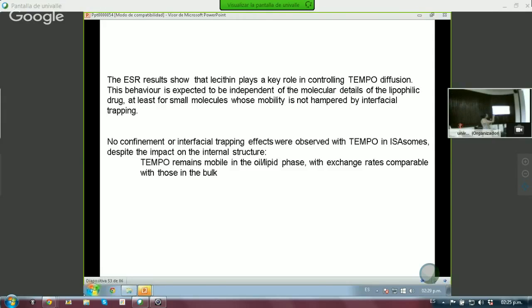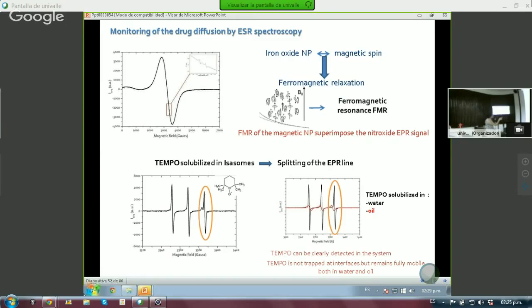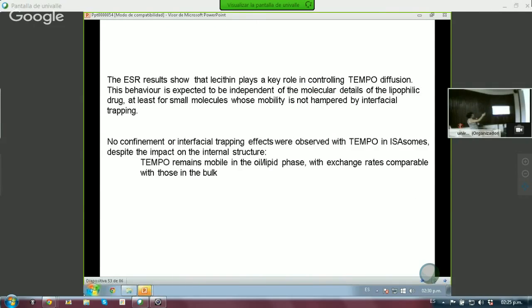It also shows that the less, since we had these. Sorry, David, can you go back? Since we said that we have this nitroxide EPR signal, so if we now, please, David, the next one. Yes, so what it shows is that the lecithin plays a key role in controlling this diffusion, which is something we expected, but it is independent of the molecular details of the drug, at least in the case of these small molecules. Well, the other thing is we didn't see any effect of confinement.